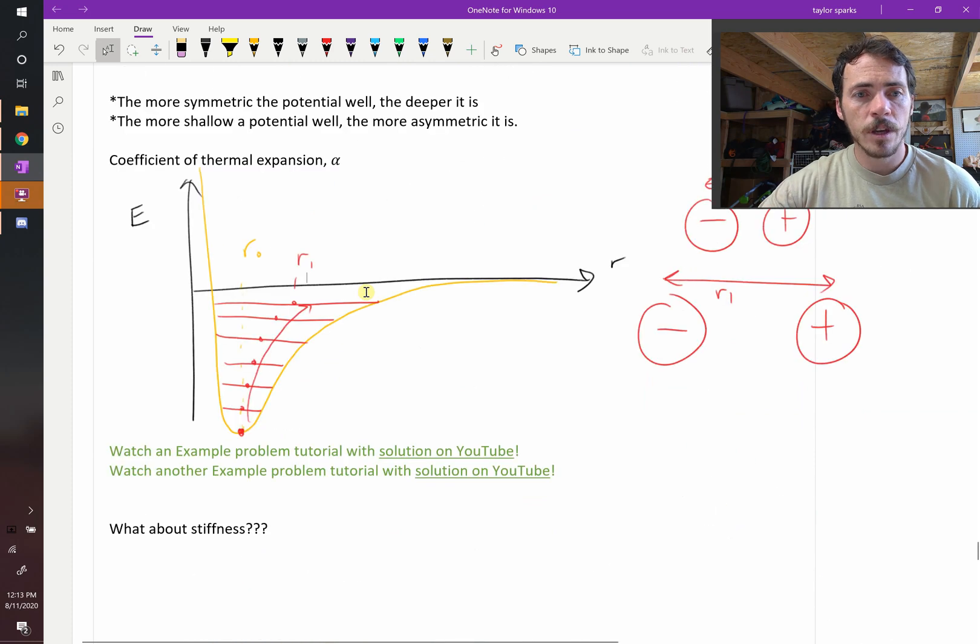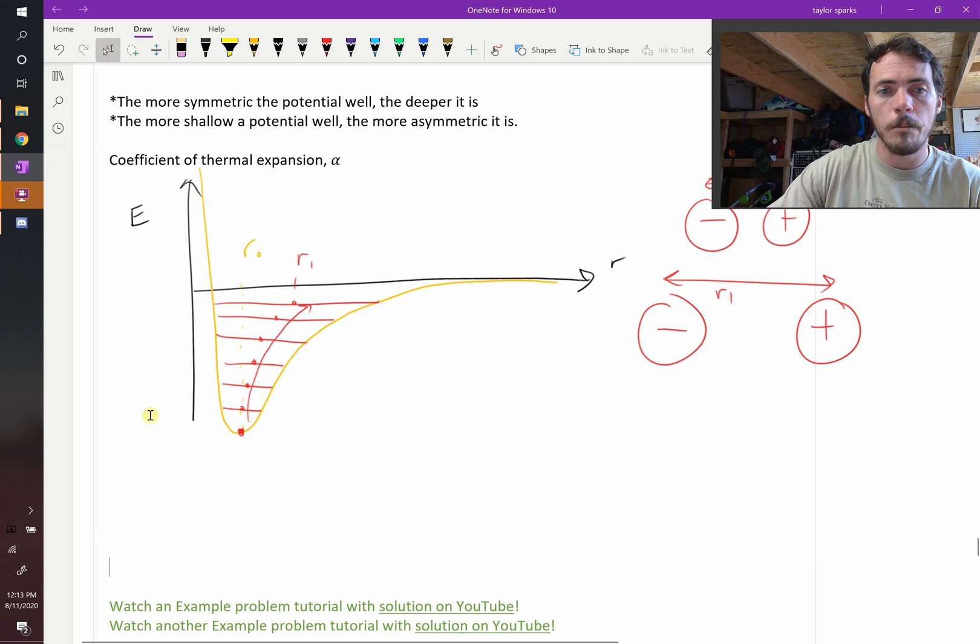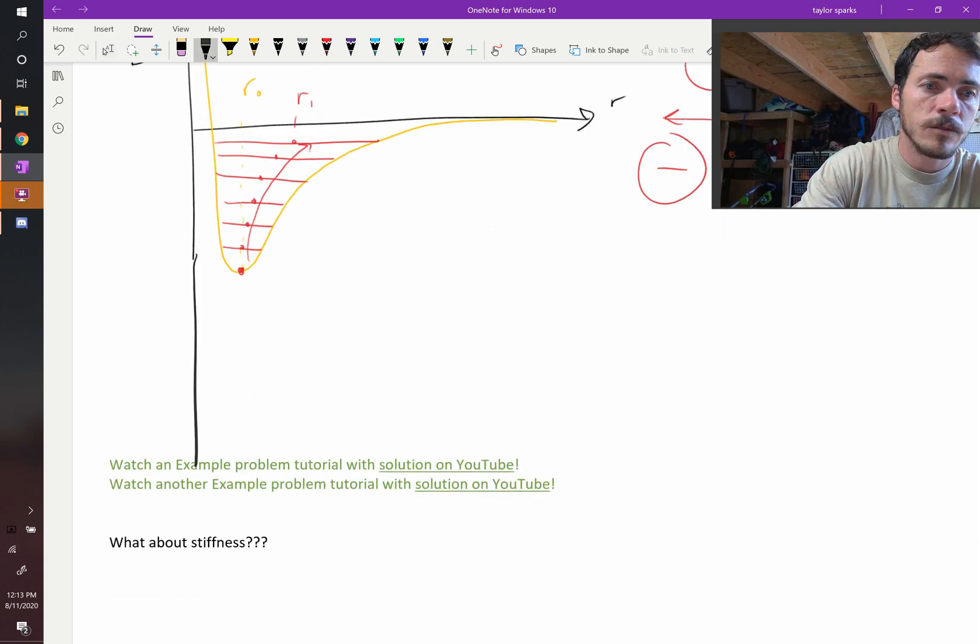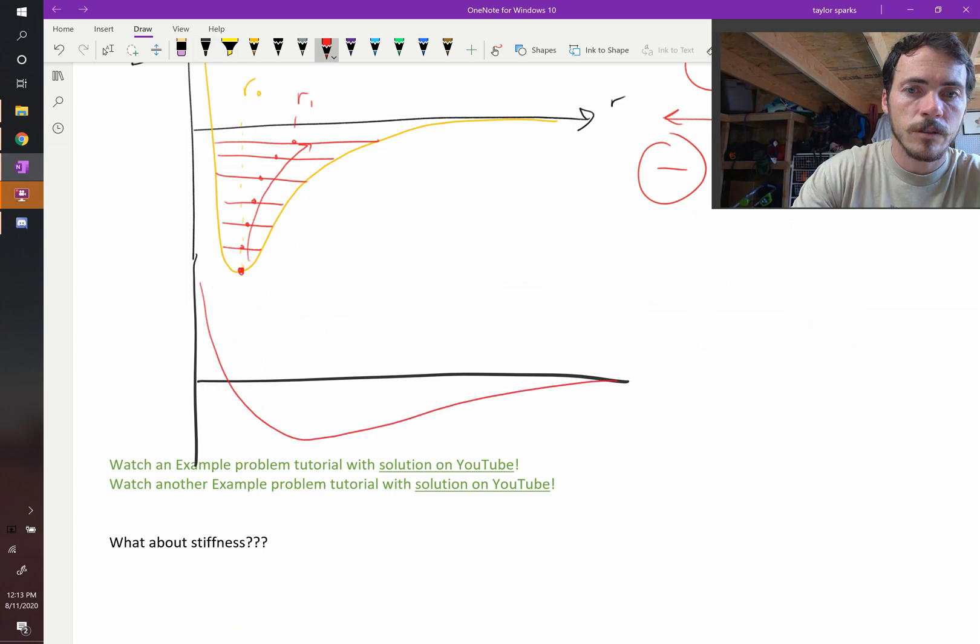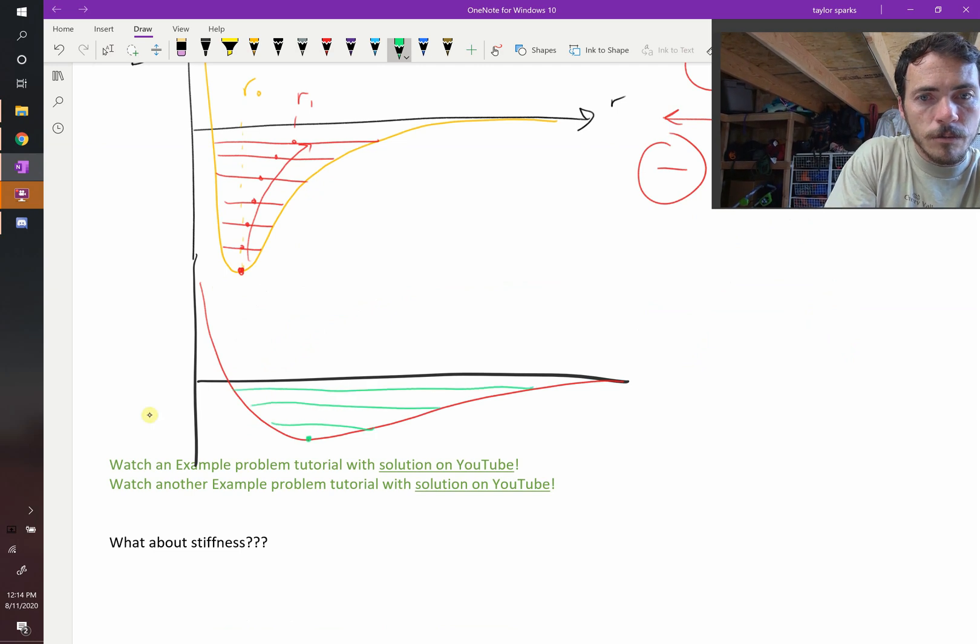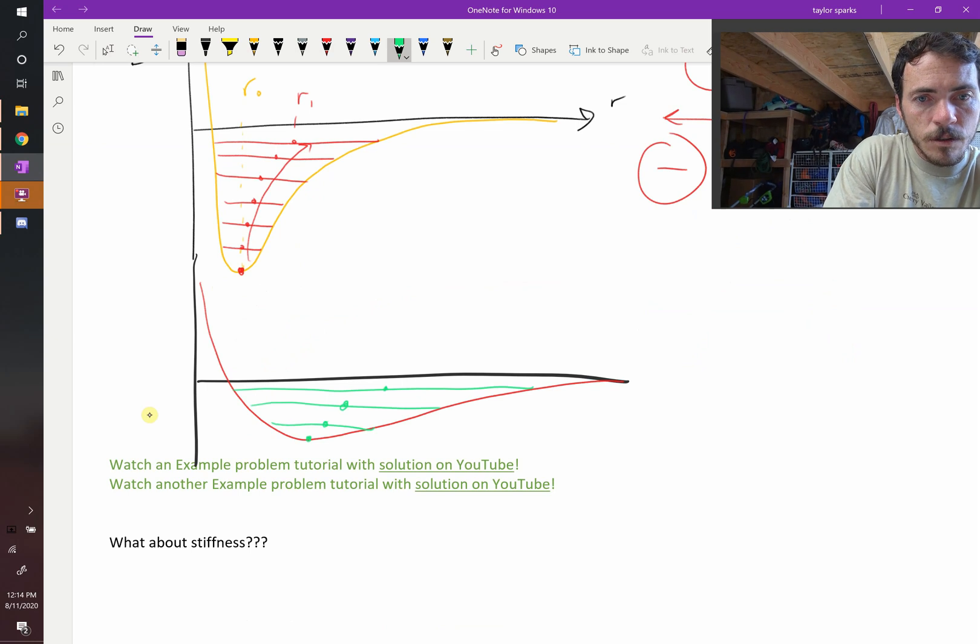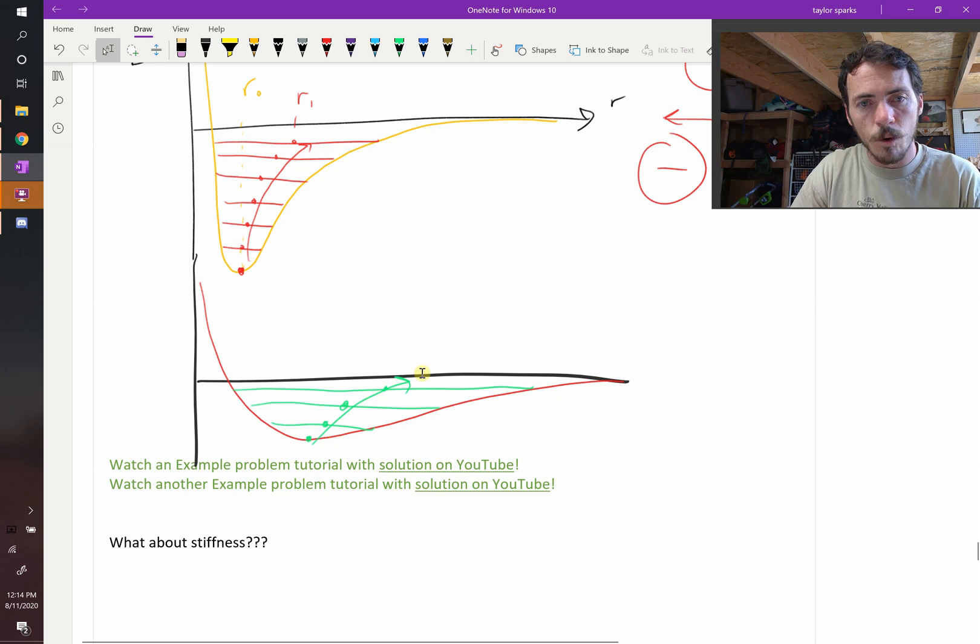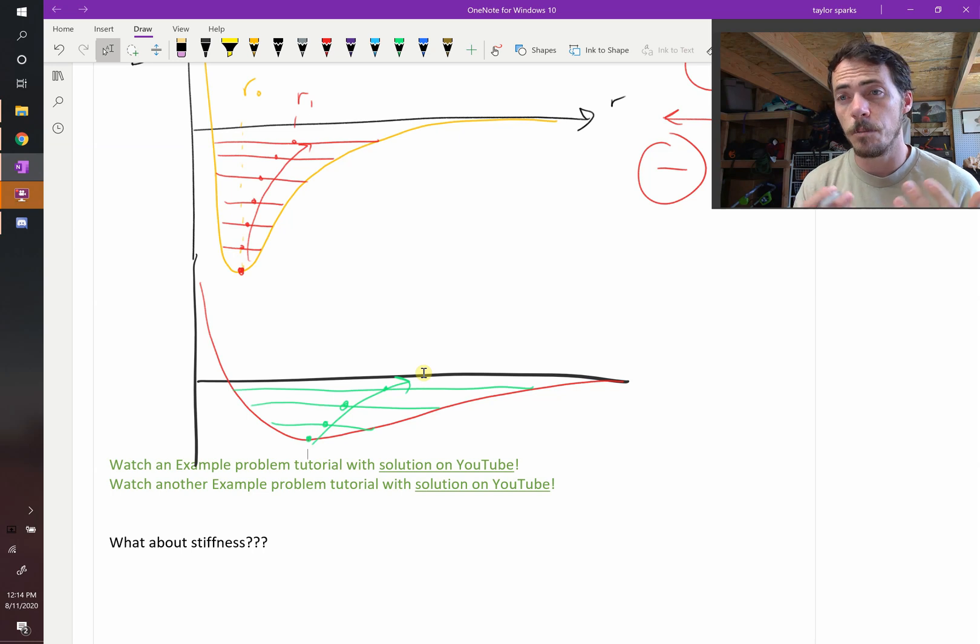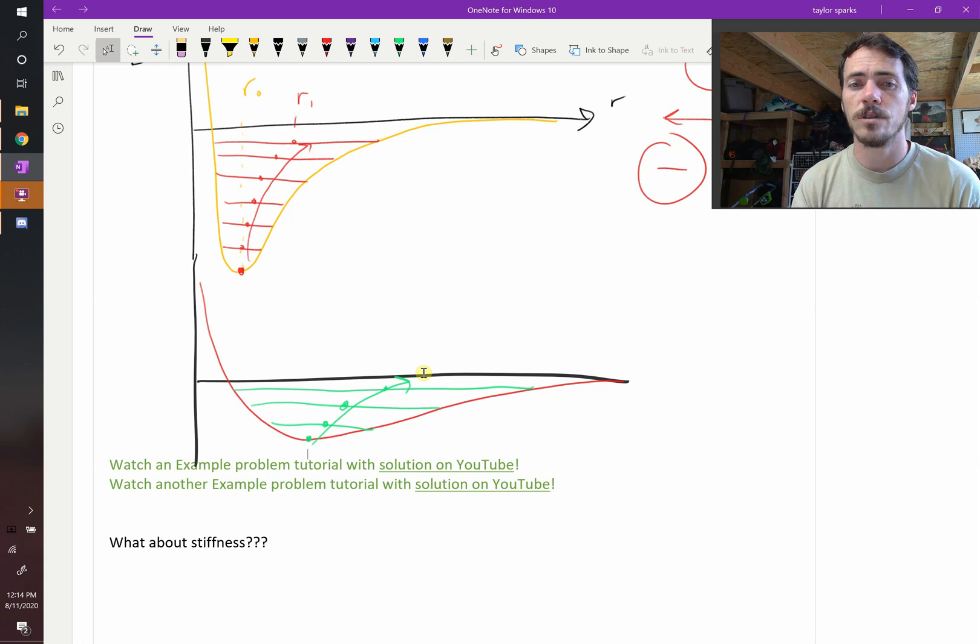Because in some cases, they might look like this, but in other cases, let's picture like a polymer or a metal, which doesn't go as deep. It might look like this. So let's draw this one over here. The polymer, or let's say it's a metal, it might do something like this. Well, now look what's happening. Here's its lowest point. And as you start to heat it up, its average position is increasing at a larger rate, right? This is less rapid onset and this is more rapid. So polymers and metals are going to expand thermally more than ceramics. Ceramics are going to expand the least, typically. Metals expand a little bit more. Polymers expand a lot more because they're the most shallow potential energy well.